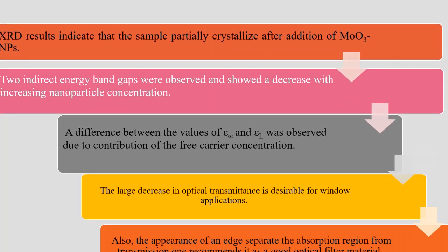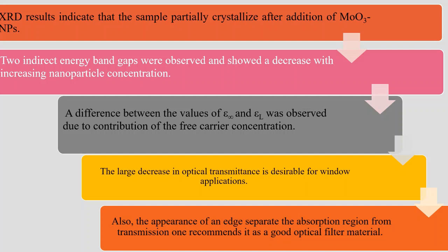Conclusion: X-ray diffraction result indicates that the sample partially crystallized after addition of molybdenum trioxide nanoparticle. Two indirect energy band gaps were observed and showed a decrease with increasing nanoparticle concentration. A difference between the value of epsilon infinity and epsilon L was observed due to contribution of free carrier concentration. The large decrease in optical transmittance is desirable for window application. Also, the appearance of an edge separates the absorption region from transmission. One recommends it as a good optical filter material. Thank you.